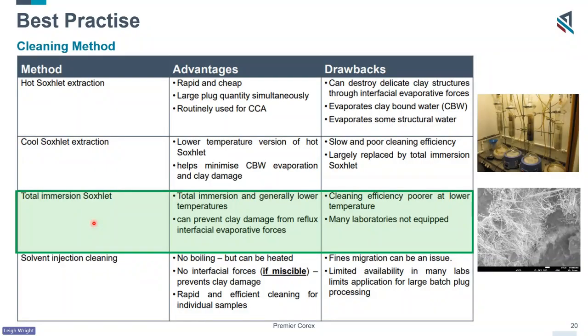So once you've taken those core samples, you've got what's the best cleaning method, and we've highlighted in green our preferred method, which is a total immersion soxhlet. I won't read through all the examples and the advantages and drawbacks. It's on screen, but the major point about getting the cleaning correct is again back onto the clays. You can see in the diagram here, we've got lots of filamentous illite coating a grain. Now, we know from experience that filaments are extremely fragile. So doing a post check with an SEM, which we'll show another example of before, it's really important to understand that you've not damaged any of that clay or any of that virginal material in the core. And that's really important and maximized with the total immersion soxhlet cleaning.